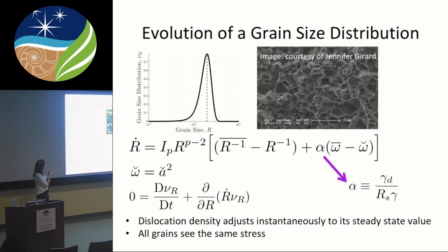typically the way we address an ensemble of grains is through a grain size distribution. This is what you're seeing here. There's grain size on the x-axis, and on the y-axis, I'm showing you how likely you are to observe that grain size within your ensemble. Mathematically, it's a lot trickier to work with this sort of continuous distribution of grains rather than just tracking each individual grain. And so just to be able to find solutions to the system or build a physical model, we were forced to make a few simplifications, but this is just our first take at this model.